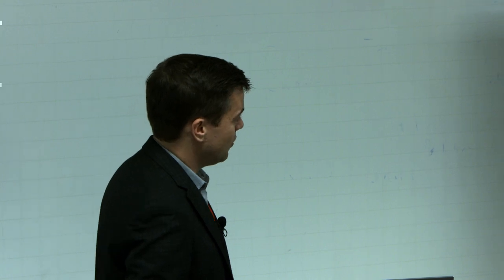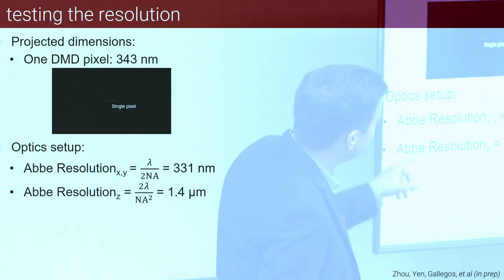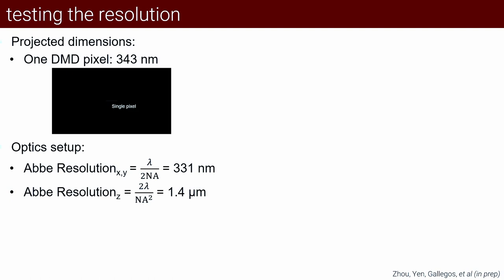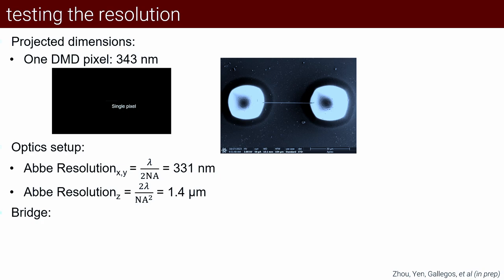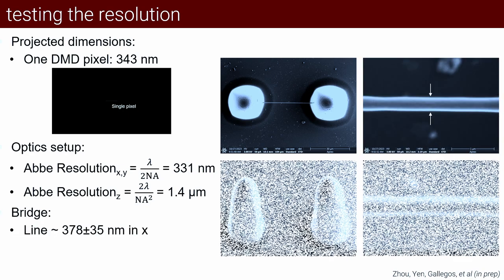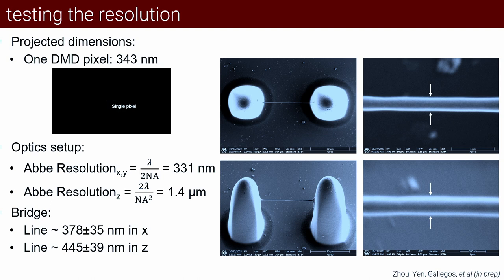Of course, the challenge if you want to move to the nanoscale is that you actually have to be at the nanoscale, right? You have to prove that you can print there. So we can do that in this initial work. It's really hard to see, but there's just one single line of pixels on this screen. We shine that in between two support structures and use electron microscopy to measure how big it gets. And what we find is that we can indeed achieve a couple hundred nanometers of resolution in all three dimensions. I can't talk about it too much publicly, but we have eyes down to hopefully getting eventually below 100 nanometers using similar techniques, which should be quite a lot of fun.